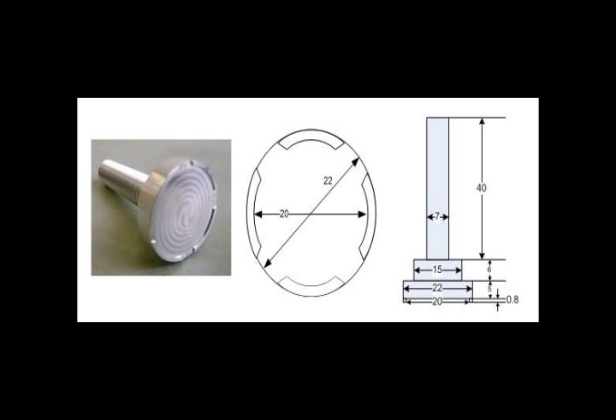In this diagram, you can see the dimensions of the BBS test pullout stub. The stub has a diameter of 20 mm with the surrounding edge used to control film thickness. The stub edge has a thickness of 800 micrometers.